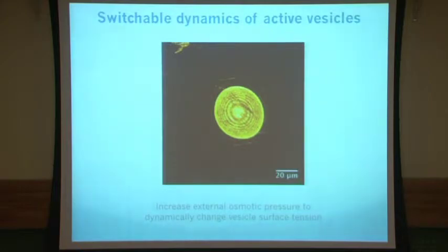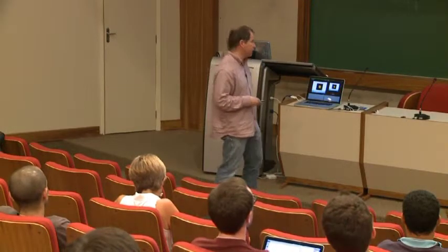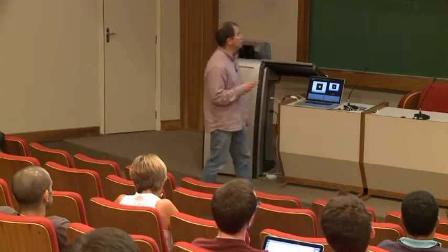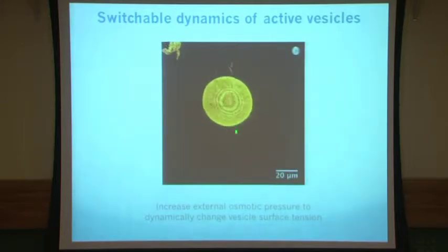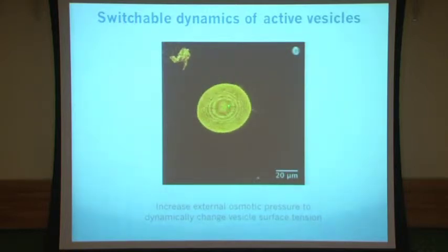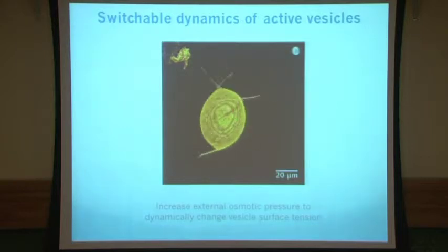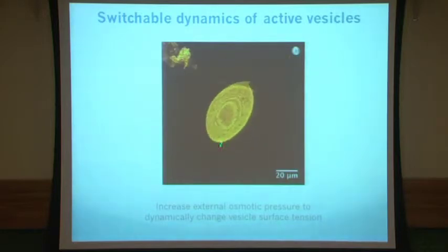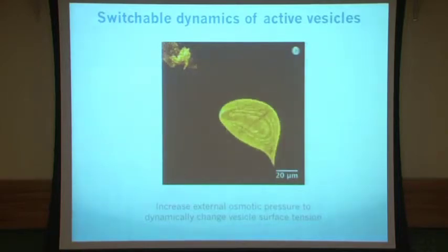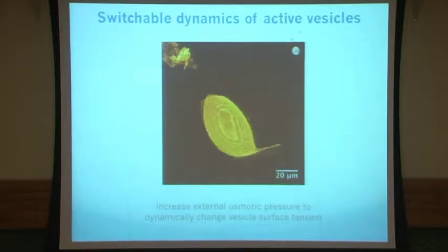And at that point, the vesicle becomes very flabby and flaccid. And so there's a lot of extra surface. Here we start with a very tense vesicle. It's essentially spherical. And then the water is rushing out, and as the water rushes out, this vesicle starts to deform. And as it deforms, it grows these kinds of protrusions, right? And so here you see 4 protrusions. As it becomes more and more floppy, these protrusions grow in size, and this really looks like something that you've fished out of your pond, but it's really a material that has just 3 components.